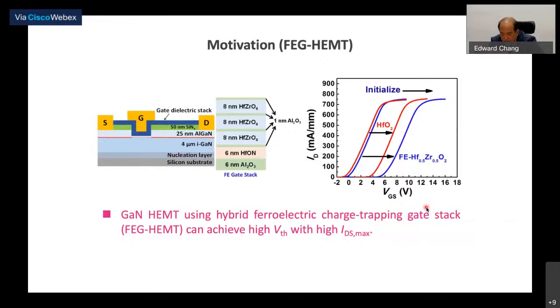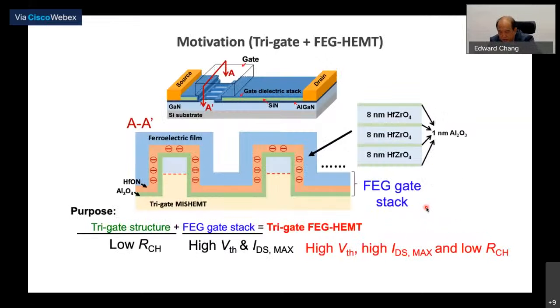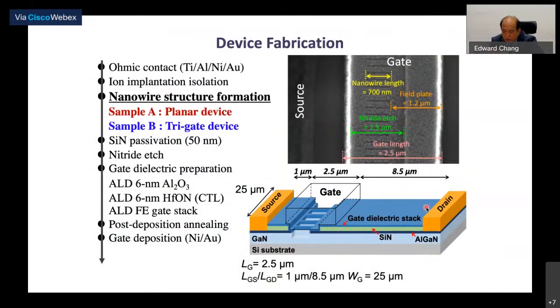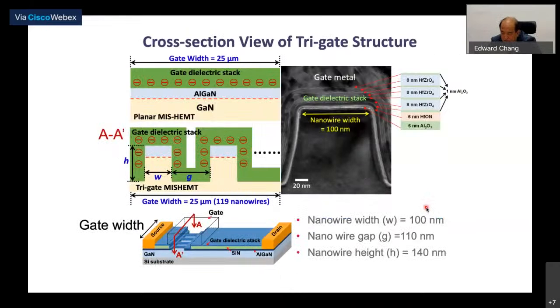We use several hafnium zirconium oxide layers with aluminum oxide inserted between, so with these small layers you can get enough ferroelectric electric field and enough current. This is a more detailed structure. By this approach, you have the tri-gate structure which gives you low channel resistance, and the ferroelectric gate stack which gives you high VTH and high current. Overall, you get the ideal device for high breakdown, high current, and low channel resistance. So this is the device, top view, overall scope, and this gives you the idea.